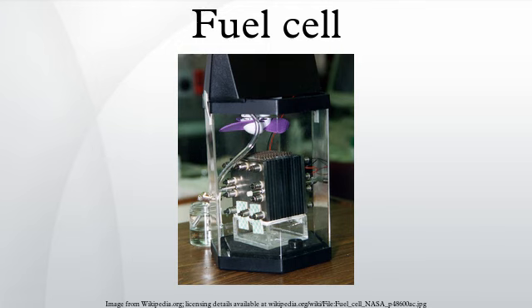A gas turbine would capture heat from the fuel cell and turn it into mechanical energy to increase the fuel cell's operational efficiency. This solution has been predicted to increase total efficiency to as much as 70%. In practice, the tank-to-wheel efficiency of a fuel cell vehicle is greater than 45% at low loads and shows average values of about 36% when a driving cycle like the NEDC is used as test procedure. The comparable NEDC value for a diesel vehicle is 22%.